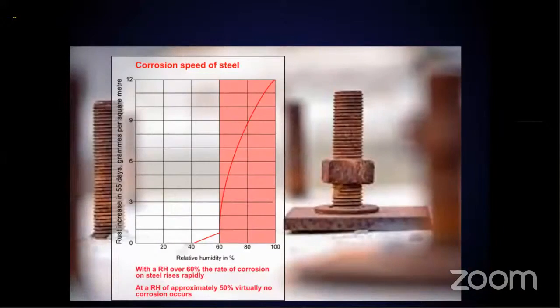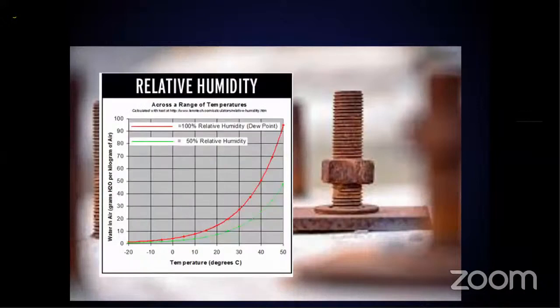Now you should also be aware that the rate of corrosion is dependent on the humidity, the percentage relative humidity. With RH over 60%, the rate of corrosion on steel rises rapidly. That is a well-known fact. At an RH of approximately 50%, virtually no corrosion occurs. This is well known. But you also see the temperature. As temperature rises, the rate of corrosion increases, as RH and temperature are interdependent.